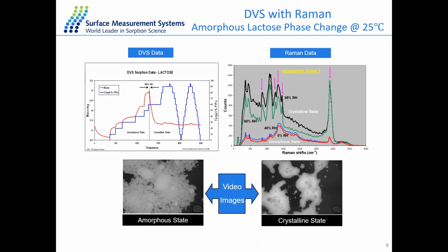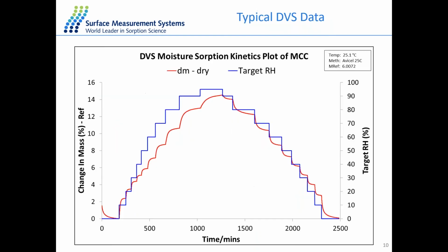So these are just some basic information about the DVS technique, and then we will focus on some typical data. This is the water sorption experimental data at 25 degrees for the microcrystalline cellulose material. The blue line here is the target relative humidity at each stage, which is on the right-hand side here. And the red line is the change of mass for the sample, so it's on the left-hand side. They are all changing as a function of time. The water sorption data we perform here is from 0 to 90% RH with 10% intervals. And at each stage, we wait for the sample to reach equilibrium.